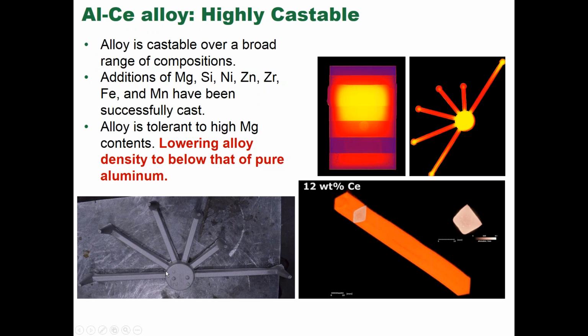As we see on the bottom left, a sand cast hot tear sample. There was a lot of work done to look at feeding ranges, hot tear resistance. We had a lot of resources, including computer-aided tomography, in order to be able to look at what was going on in the alloy and how it varied over various feeding distances. So we had some extraordinary resources that helped us understand these alloys and how to further perfect them.